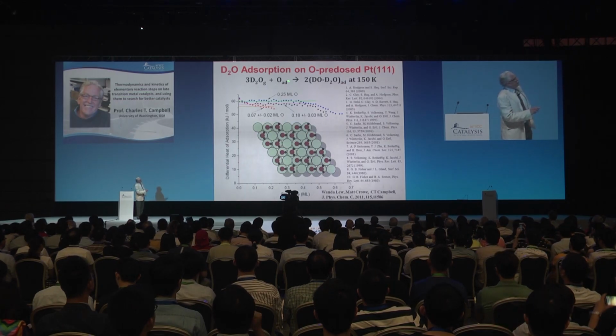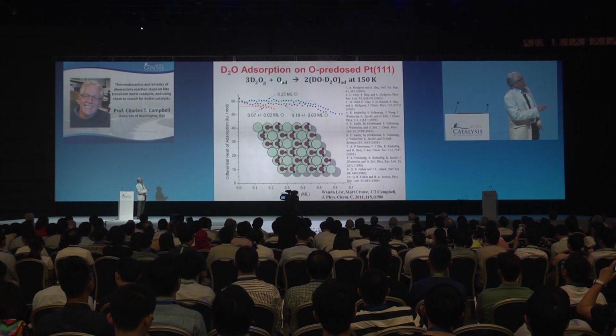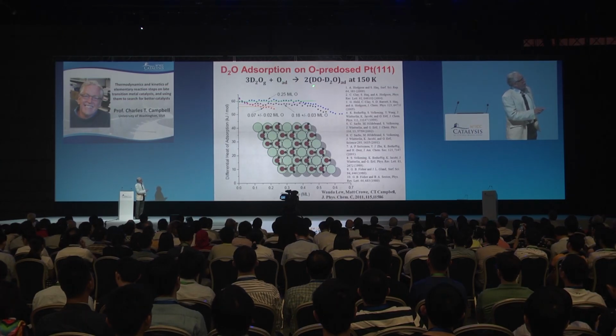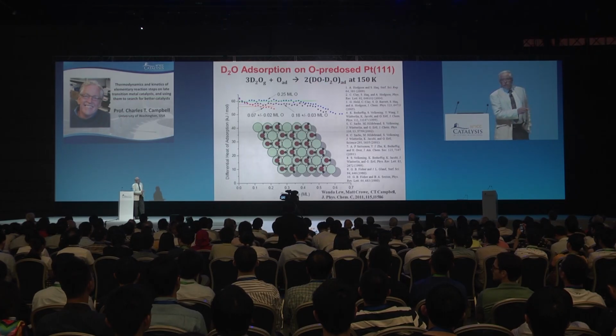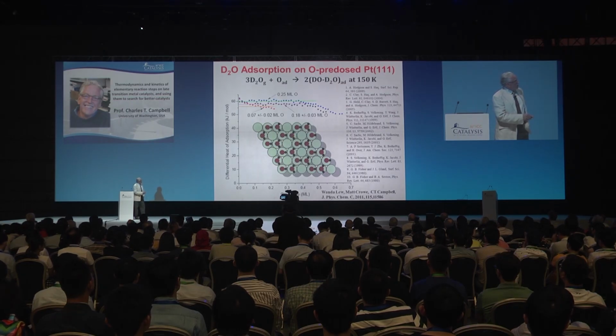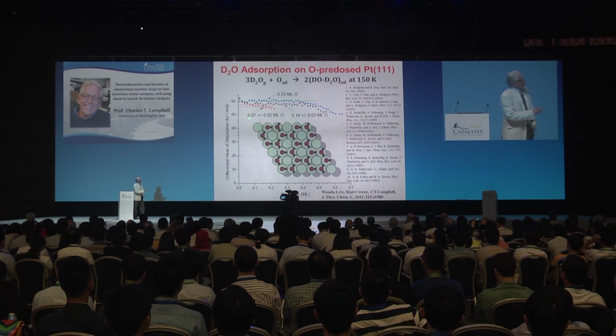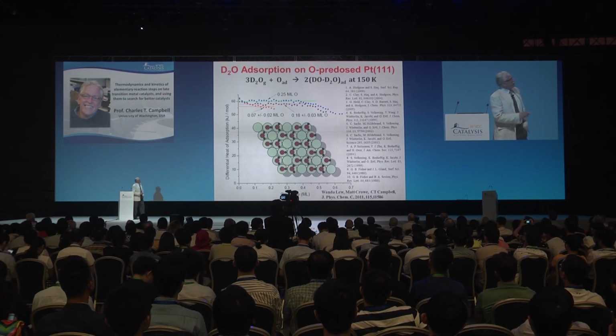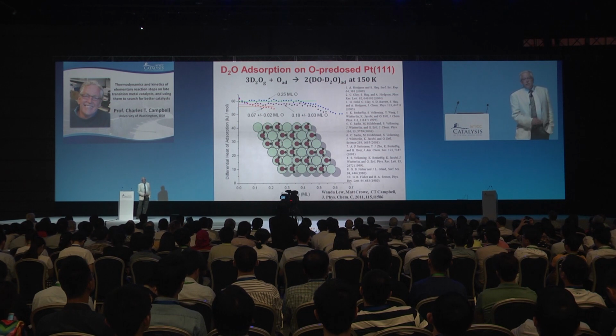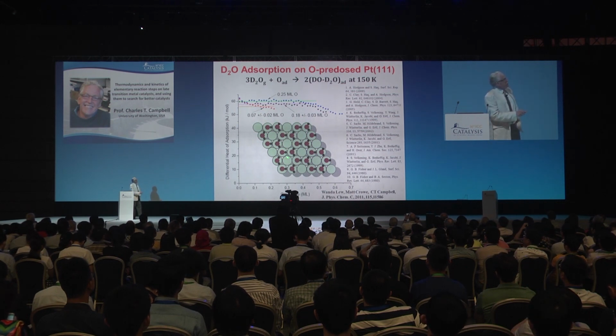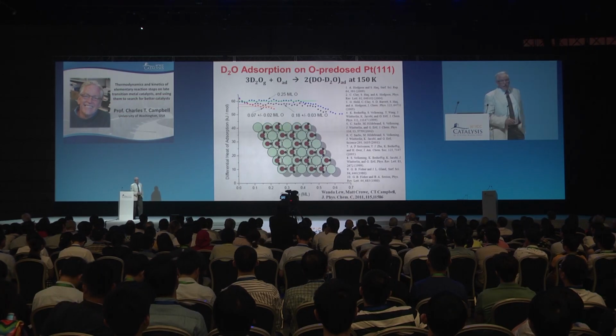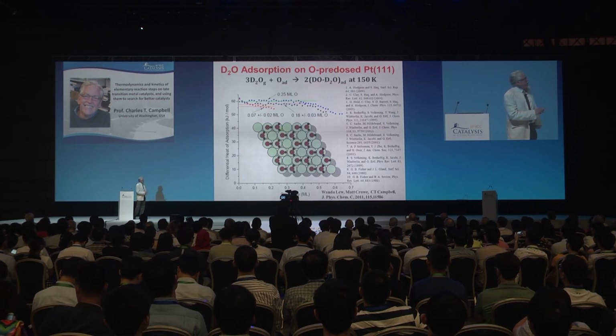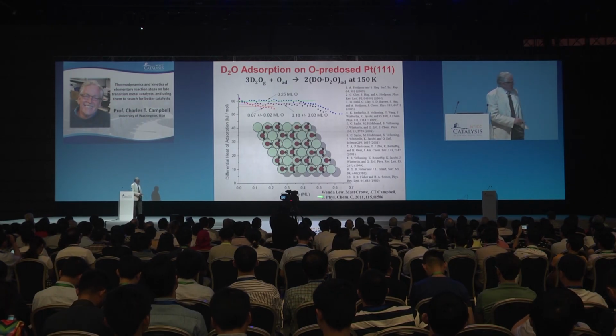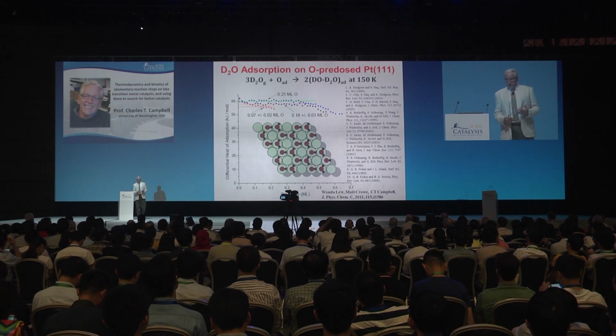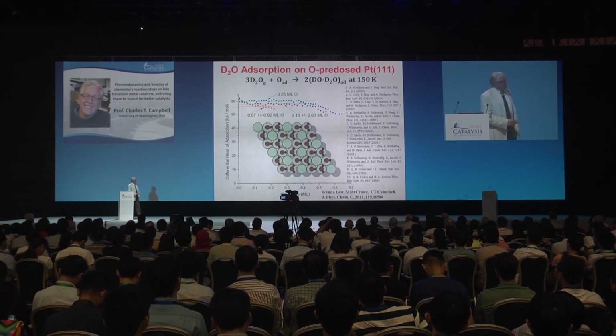For example, it's known that if you have a platinum surface and you adsorb oxygen atoms first, and you dose water to that, you make this one-to-one hydroxyl-water complex on the surface, with the structure shown here, where the hydroxyl groups are hydrogen bonded to waters. It doesn't matter if you start with a low oxygen coverage or the saturation amount of oxygen on the surface. As you dose water, you get essentially the same heat of formation, because you make islands of this structure locally, no matter where you start in oxygen coverage. I'm going to talk about coverage here in units of monolayers, always defined as the number of adsorbates per metal surface atom.